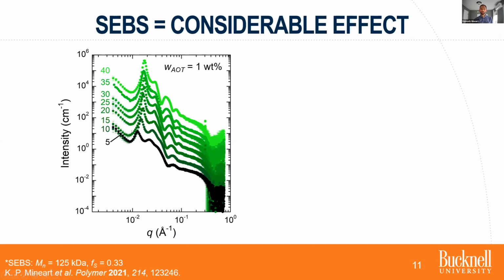And so as you can see here qualitatively, the sharp peak at low Q moves to the right in terms of Q space. And so we're seeing a decreased spacing between polystyrene domains. The broad features in the center are moving to the left. And so we're seeing polystyrene domains that are getting larger with concentration.